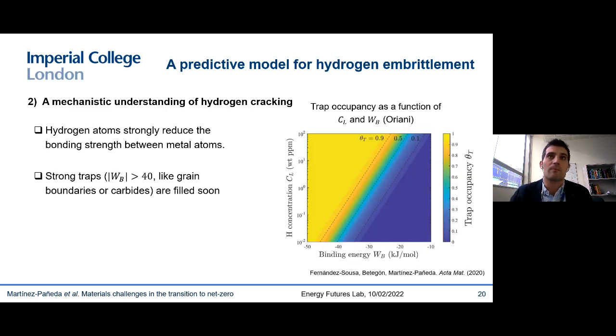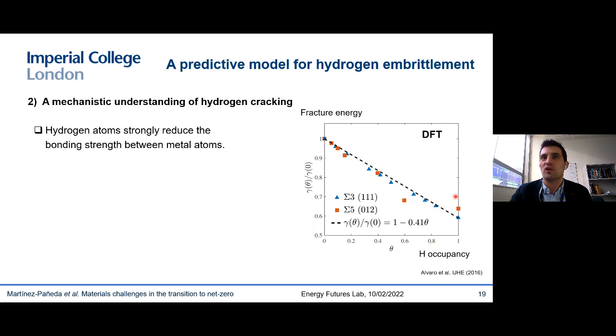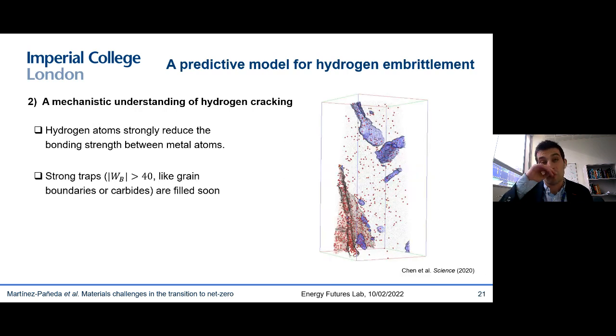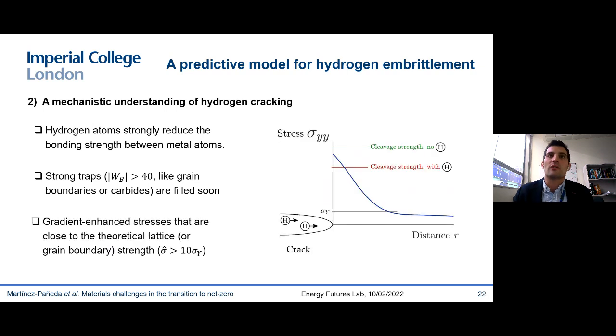And the answer to that comes from the chemistry. We can take the thermodynamics of trapping based on Oriani's equilibrium, and we can plot the hydrogen concentration versus the binding energy, which is a measure of how energetically favorable it is for the hydrogen to go to that trap, like a grain boundary or a carbide. And then this is the trap occupancy. And you see that for strong traps, like grain boundaries, which have binding energies of -40 or smaller, with very little hydrogen, like 1 part per million, you can already see that the grain boundary is going to be full. So if you come back here, you're always going to be moving in this regime, and your grain boundary is going to be quite weak. And this is, by the way, what they see in experiments. This is a very recent Science paper where they use atom probe tomography, and you can see this thing in red is a grain boundary, and the grain boundary is full of hydrogen atoms, which are these red circles. So that takes me to the third and last ingredient.